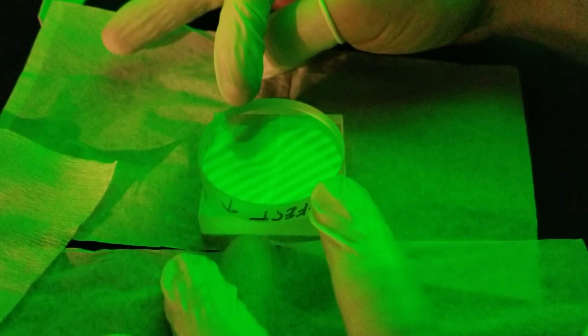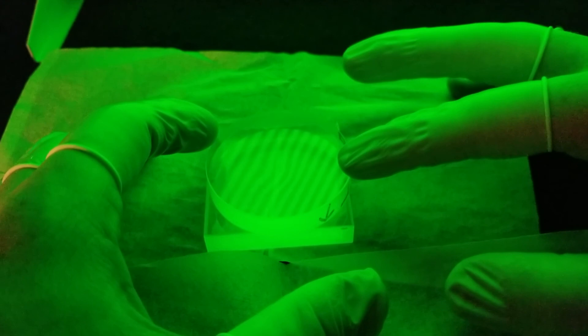If there is a bump or hole, there will be a deviation in one direction of the fringes visible. If some light pressure is applied, the number of fringes will increase or decrease if there is a defect.